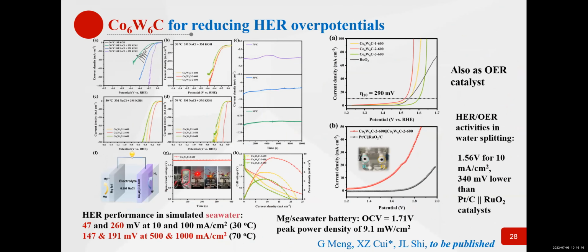And then another advantage of this material is very high current density output. For example, at about 150 or 190 millivolt, the current density can be as high as 500 and 1000 milliampere per square centimeter at 70 centigrade. And these materials, we think it is very hopeful in the future in industrial use, because it is very active and can produce very high current densities.